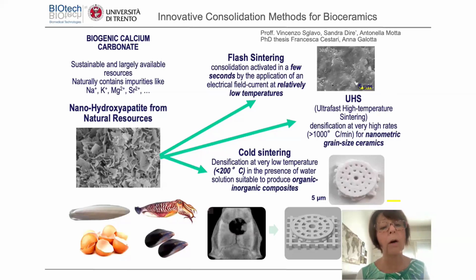And with the help of Professor Vincenzo Sglavo in our department, specific processing methods, flash sintering and cold sintering, were designed in order to produce bioceramics, reducing the temperature needed. Usually to obtain ceramics, sintering is done at 700, 800 degrees, even higher temperature. But of course, we want to be more sustainable, reducing the energy involved. So new systems are designed trying to reduce as much as possible the temperature needed.